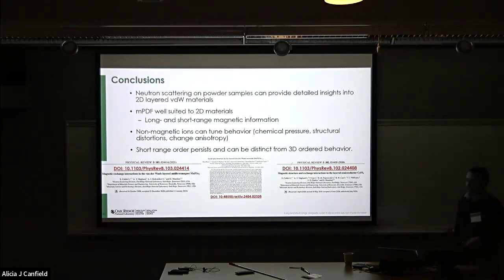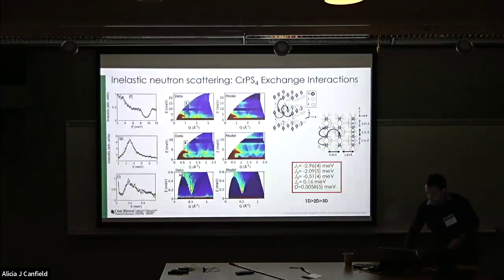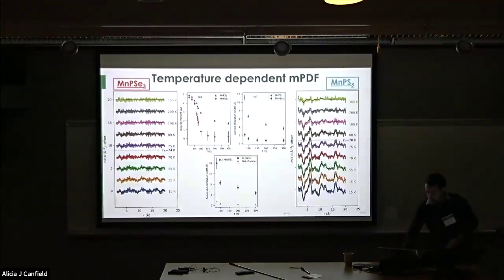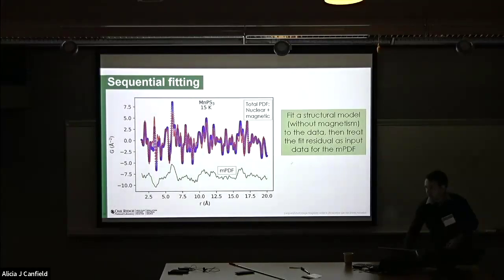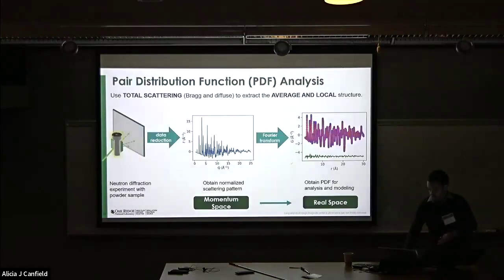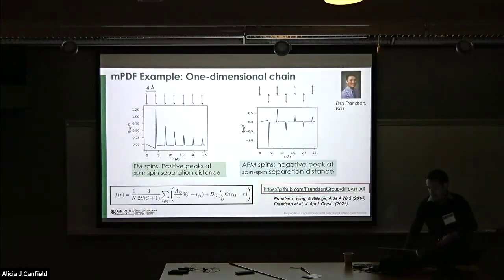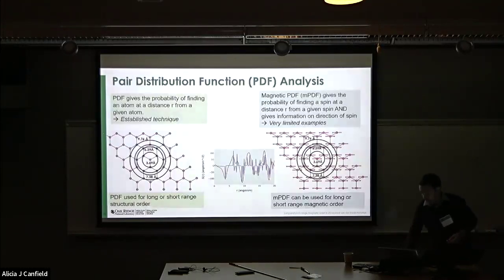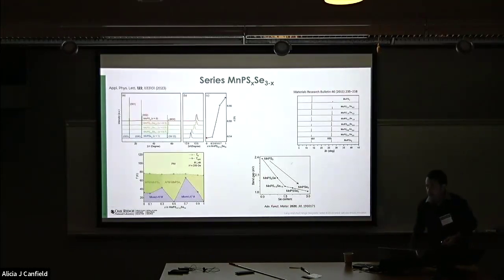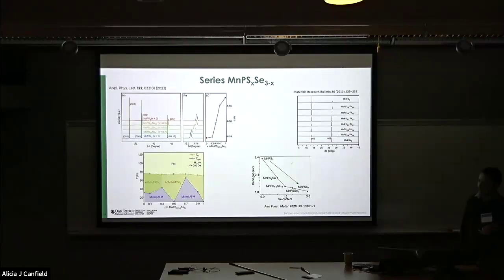Yeah, but that's interesting. Can I ask a very basic question? When you changed X in this series, you did it in integer and half-integer steps. Are they all ordered compounds? And what happens in between the integers? That's a good question. We don't know. These are very nominal values. We showed these just because it's the easiest thing to do. We're assuming the sulfur and selenium are going in randomly. We don't see any indication that they're starting to order, but we haven't looked carefully enough to really say that. In PDF, you would see that structure. We did the measurements the wrong way around. We looked at the doped samples with the instrument that gives you bad real space resolution.